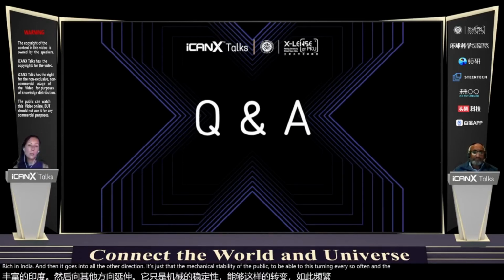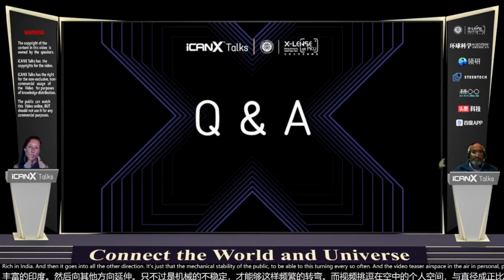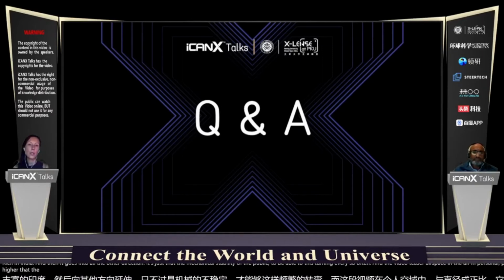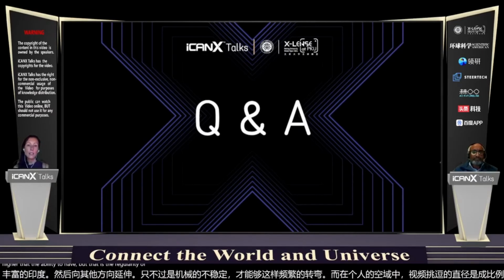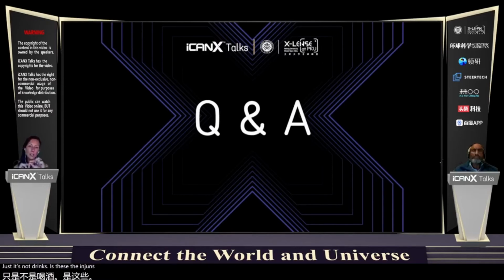And the period is inversely proportional to the diameter. So the smaller it is, the higher the period you have. But yeah, the regularity is quite good. So it's like a superlattice structure. Just it's not twins. It's this interlayer of indium that you have in between.